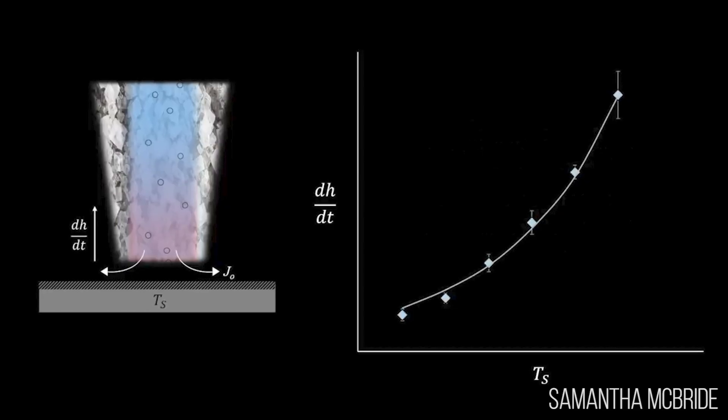So you're able to take those two models and solve for the rates of growth of the legs with time as a function of temperature and the evaporative flux. The model actually worked almost surprisingly well for the data, which almost never happens, so that was exciting.